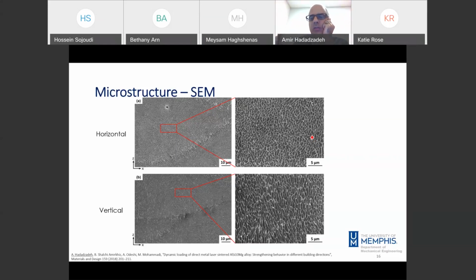And in this type of structure, we have an aluminum matrix. So these dark regions are aluminum matrix. And they're bounded with eutectic silicon walls. The brighter area is the eutectic silicon walls. And if you consider the scale bars that I'm using here, 5 micron, and in lower scale 10 micron, we can get an idea regarding the scale of these cells.